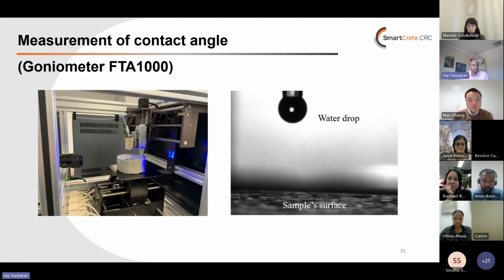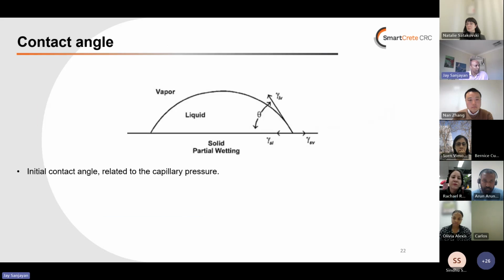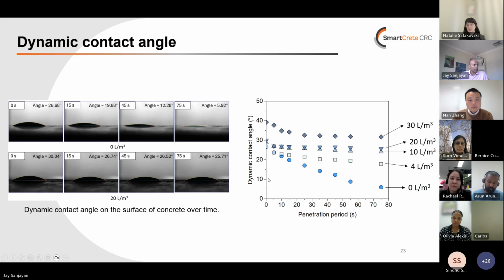In addition, we also measured the contact angle, that is the angle between the water and the surface of the concrete, using our equipment that we have at Swinburne. That's the wetting angle between water and the concrete containing waste paint. You can see here the contact angle, the bottom curve with 0 liters. With the penetration period, with time, the angle reduces, and then the water gets absorbed. That is the first picture you see on the left-hand side. But with increasing amount of paint in the concrete, you'll see that angle increases. And that is the major reason,